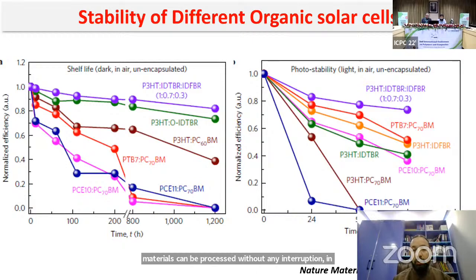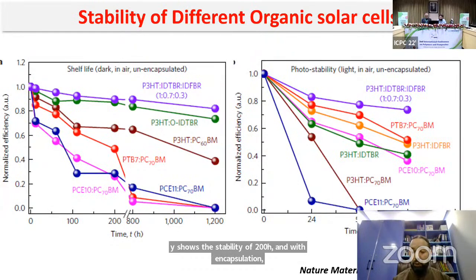To our surprise, what we have seen is that the devices with these ternary components show the best stability. They were quite stable even on the shelf, with a limited drop in performance over 1200 hours, while under the light they show stability up to 200 hours. And with encapsulation, we think these materials can work for many years without any problems.